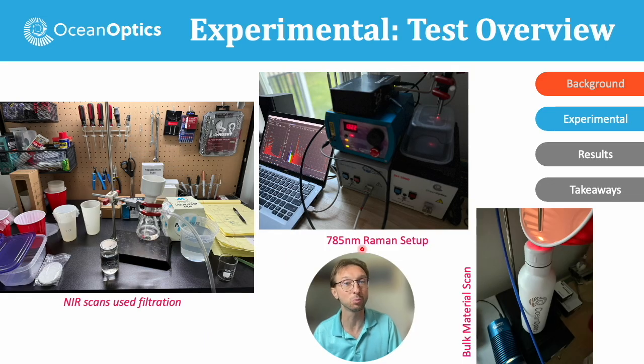And then this is one of our setups for 785 nanometer Raman. You can see the laser here and our laser and the test computer. And then this was the reflection setup, an example for the bulk material scan. So we did also look at the bulk materials because we wanted to see if those peaks that we were seeing in the fluid correlated to any peaks we were seeing in the bulk material naturally.